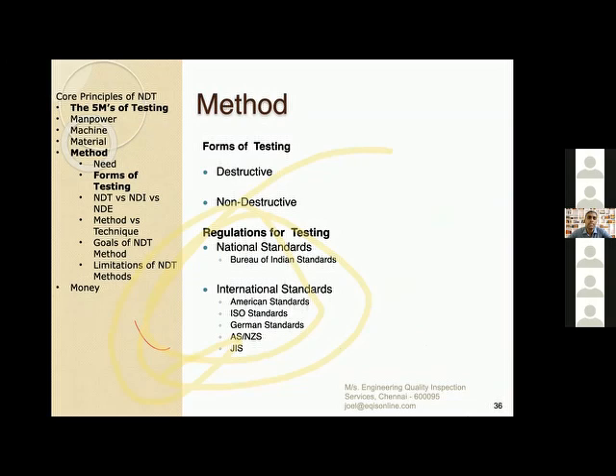there are very funny standards. For example, I have seen a standard for an aluminum specification which says you can have porosities. The number of porosities that can be accepted is 3000 times the thickness of the metal, which means, let's say I have a 10 mm thickness, I can allow 30,000 porosities in that component, which means the standard is trying to say, don't consider porosity a defect. If the component is full of pores, please accept it.